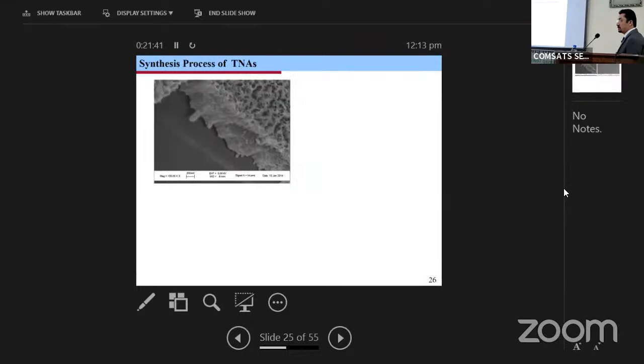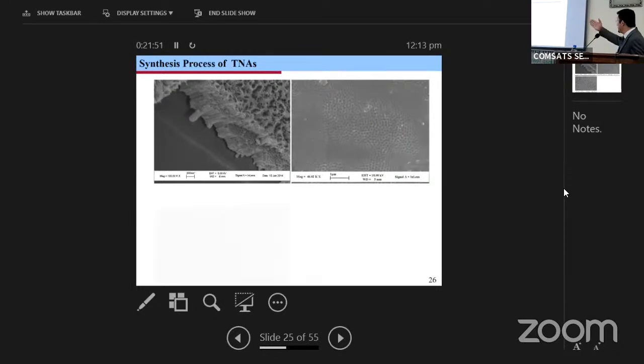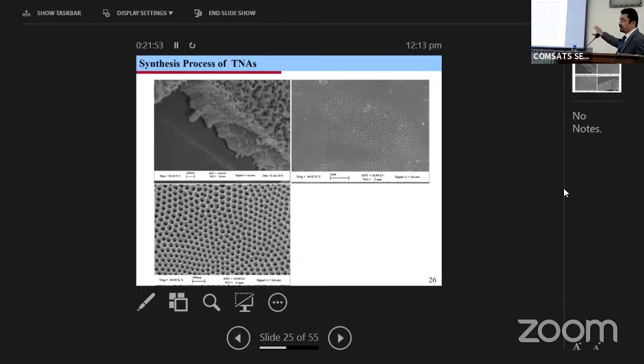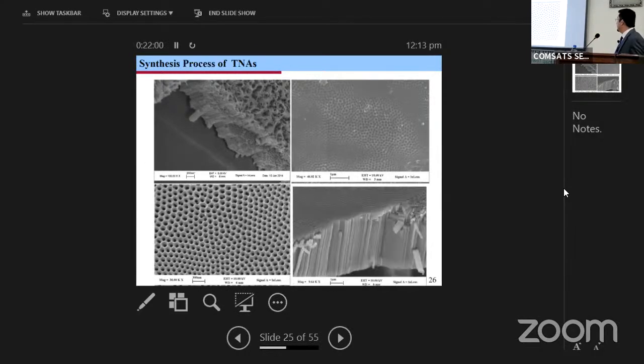this is the nanograss. In the first anodization, when we did it, this was nanograss and it was not clean. So to clean it, we peeled them out, and I used second anodization. And in the second anodization, these are the footprints. This is the second anodization. After the second anodization, we have no grass, and we get very clean titanium dioxide nanotubes. This is their top side, and this is their lateral side.